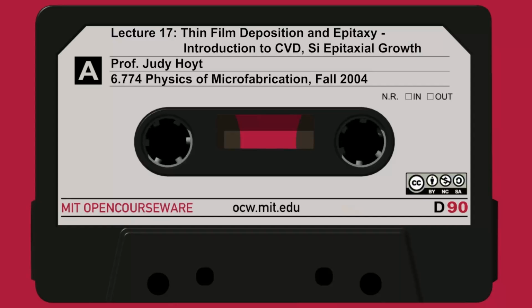If I plot the growth rate on a log scale versus 1 over T, the K sub S term is just going to be a straight line, because I'm taking the log of an exponential. It's directly proportional to 1 over T. So down in this region, the slope is directly proportional to the activation energy.